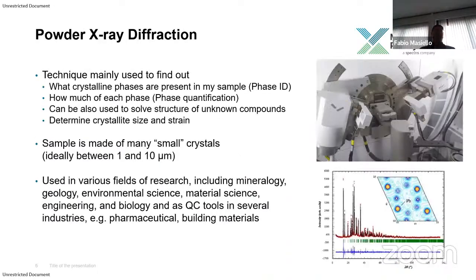Moving to powder X-ray diffraction, which I mentioned before, you need a polycrystalline sample. And this technique is mainly used to find out, first of all, what crystalline phases are present in my sample. This is what we call phase identification, phase ID. You can also see how much of each phase is present in my sample, so phase quantification. It can also be used, as with single crystal diffraction, to solve the structure of unknown compounds, and it is also used to determine crystallite size and strain in your crystals.